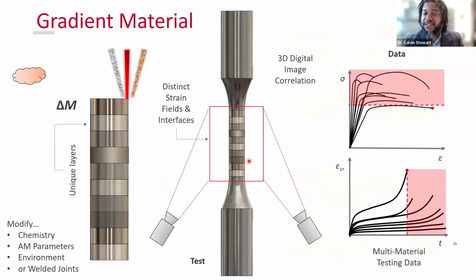And then the final crazy test method that we've been leaning into and we built something for is what we call the Delta M, the gradient material test setup. This is the idea to say, hey, if we can parallelize boundary conditions, if we can make stress a gradient or temperature a gradient, what about the material itself? What about creating functionally graded materials where we change the additive powder on the fly and subsequently change the chemistry layer by layer in a part?